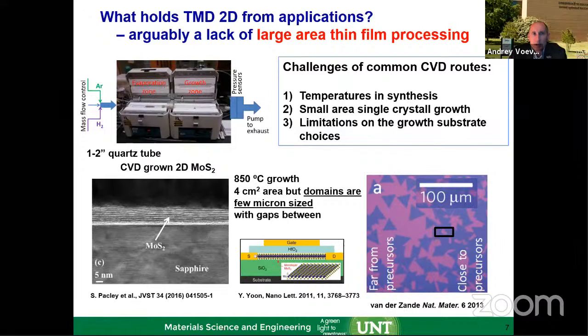The problem is that if you follow the literature on 2D materials fabrication, you will find that most of the processes, like 90% of them, use high-temperature growth. CVD, chemical vapor deposition, is one of the most popular techniques, where you take gases, which can be carbon-containing gases, and feed them into tube furnaces with a catalyst, and at 800, 900 C the gases decompose and you start forming graphene if you're using a copper or nickel substrate. Or you can grow molybdenum disulfide or tungsten diselenide if you're using sulfur and selenium additions together with the metals.